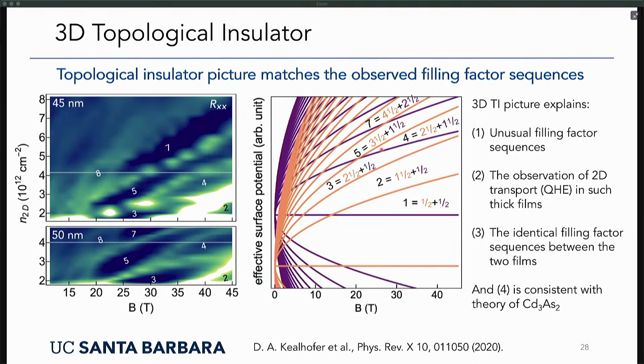Okay, and that explains why we get these unusual filling factor sequences. So in the middle here, in the intermediate magnetic fields, you can see, for example, this very strong ν = 3 plateau, but you can see how some of the even ones might be absent because you're close to these crossings, and so they're poorly resolved. Okay, so this picture of this 3D TI, what you expect in the case of having an offset in the surface potential, explains exactly what we're seeing.